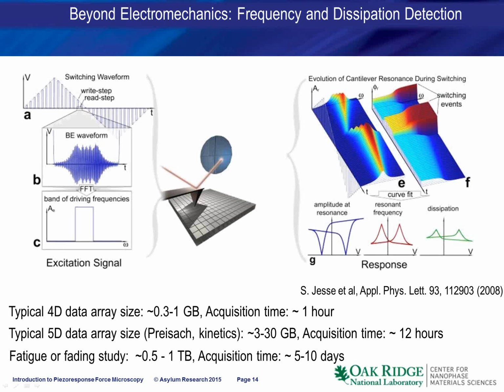So we measure the response at each location, both as a function of frequency, the band excitation dimension, and as a function of time. And during this time, our waveform follows this triangular wave. Once we've done it, we can fit our band excitation data in order to extract the amplitude at the resonance frequency, and the dissipation as a function of voltage during the triangular sweep. So amplitude at the resonance gives us the classical PFM signal, and resonance frequency and dissipation are the new information channels that give us insight into the loss mechanisms and changes in the material structures during the voltage effects.